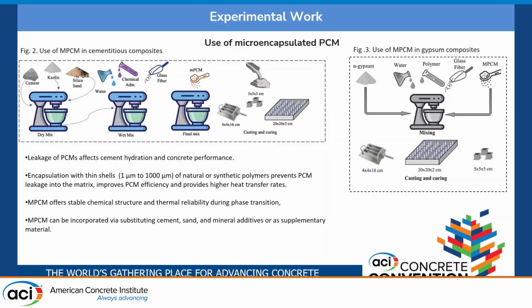So we have used these microencapsulated phase change materials in different types of composites, as you can see in this figure too. We did some cementitious composites. We first mixed our raw materials, and then we added our chemical admixtures and water, and then finally we added some microencapsulated phase change materials, and we casted and cured them. We also use this in gypsum composites as well, as you can see in figure 3.